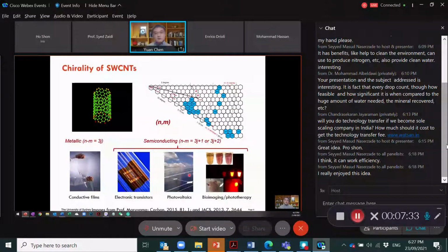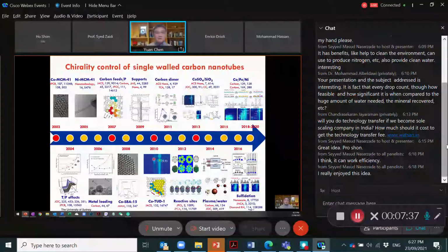Now, so that's actually quite difficult. So that's why we spent so many years trying to solve the problem. The way is we control the catalyst and the metal clusters, and eventually using the metal cluster to control the growth of nanotubes. We actually now can produce some specific types of nanotube. They are semiconducting with very high purity, and so those can be applied into different electronic device applications.